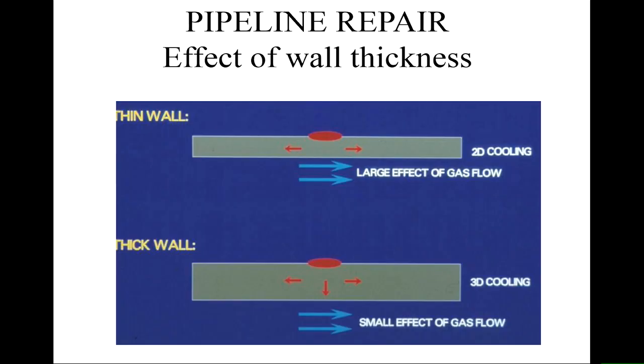And the reason we're doing that is to do with the thermal sink that is in the pipe system. So if you imagine a thin wall tube and you deposit the weld metal, most of the heat is conducted along that tube and not into the thickness, and you get a two-dimensional cooling process there. So you've effectively got the gas flowing beside the hot metal and the heat going from the metal into the gas, and the gas takes that away. So if the gas flow is increased, there's a large effect of that gas flow on the cooling rate.